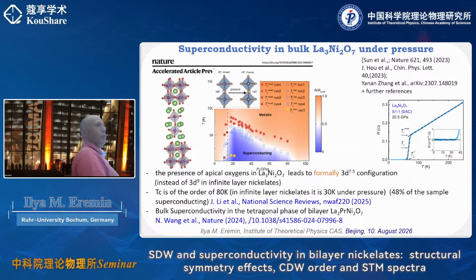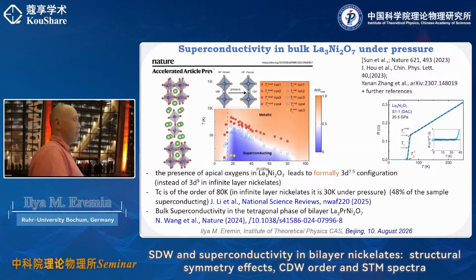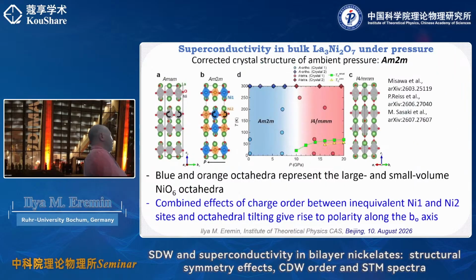It was first shown by Liling Zhang and collaborators. And we know that this has meanwhile been reproduced by multiple groups. Moreover, if you replace one lanthanum by praseodymium, then it is believed to be 100% superconducting. The situation is more stable in this case. Okay. Now, let me tell you why. Let me show you one very recent slide. Since the beginning of this year, there have been growing doubts whether the actual phase is Amam. So this would be this phase.